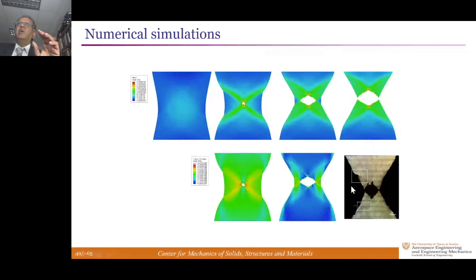And I'm running out of time, so I'm going to show just one computational result. This was done by Andrew Gross in the first Sandia challenge. If we use this idea that the local strain to failure is extremely high, we're able to do predictions. The blind prediction is the black line, the experiment is the red line. We're able to do reasonably well, first Sandia challenge, second Sandia challenge.